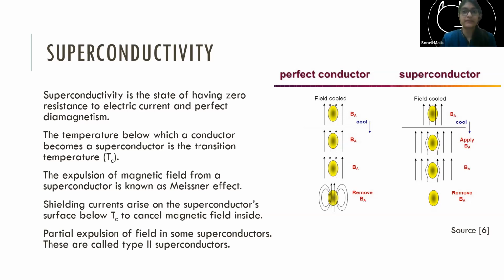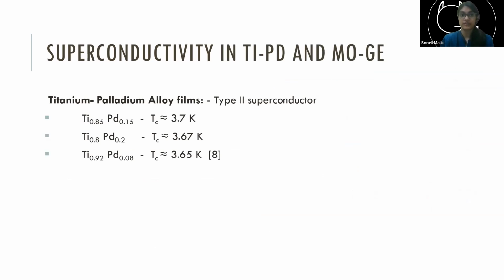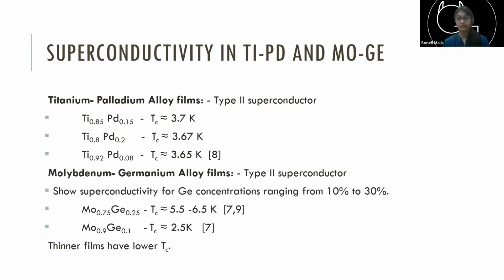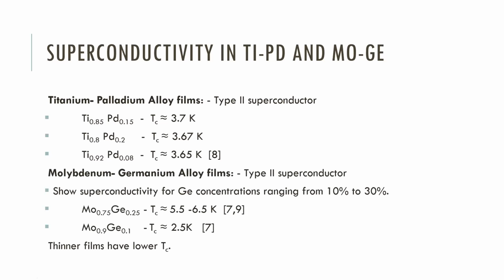So I mentioned that here because the two superconductors that I worked with, titanium palladium alloy and molybdenum germanium alloy, they're both type 2 superconductors. So I'll start with a little literature review. So based on the work people have done on titanium and palladium, they have shown superconductivity around 3.7 Kelvin, and the concentrations especially are really important. You see the concentrations here are changing just a little bit, and that's causing a significant change in the transition temperature. Right, for molybdenum germanium alloy also, again type 2 superconductor, and in this case,